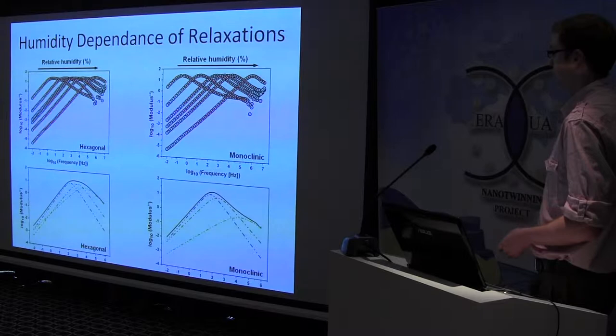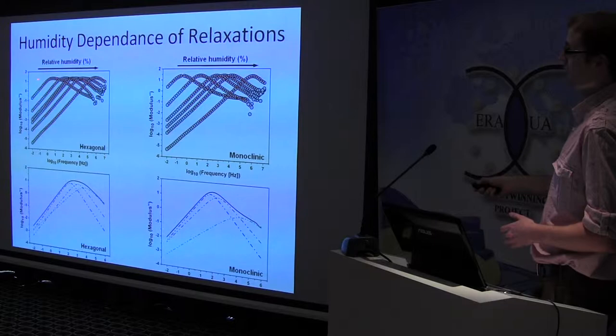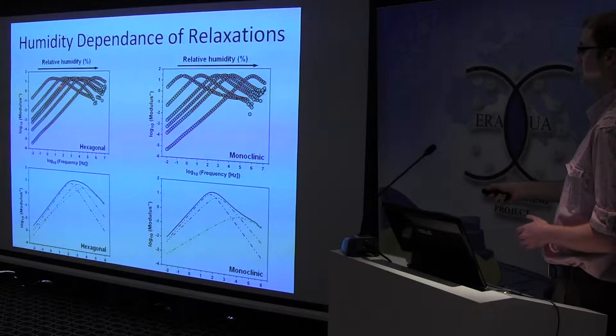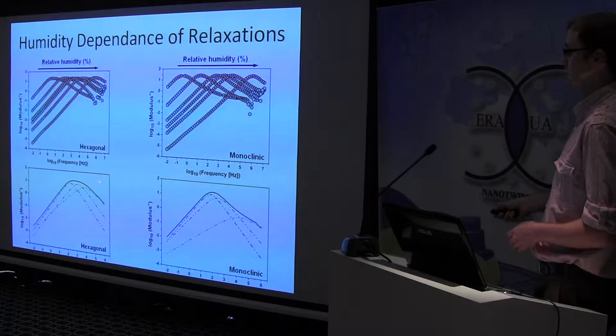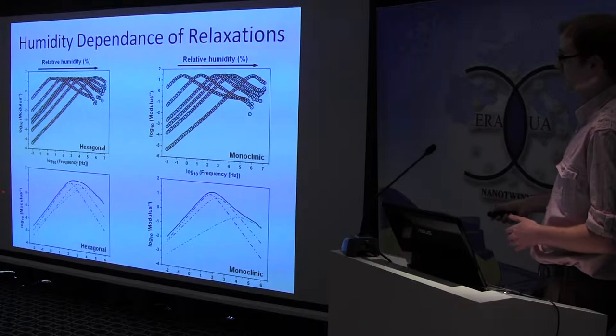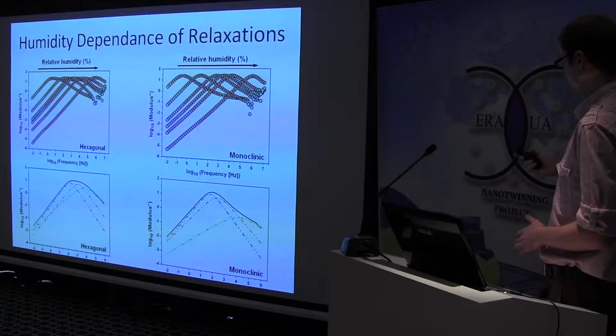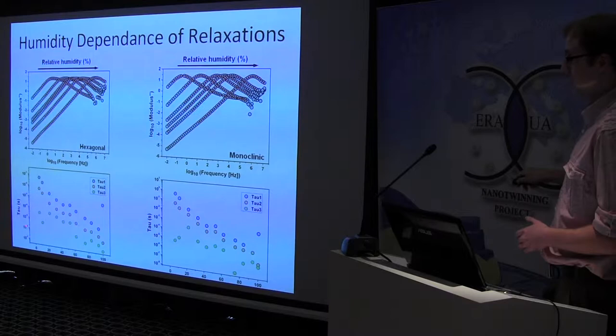Here you can see the humidity dependence of the dielectric response in modulus representation. Here is the sample at 6% of relative humidity and this is the sample with 100% of relative humidity. You can see that there is a shift to higher frequencies with increasing relative humidity. Here you can see a single modulus which consists of three different relaxations with three different characteristic relaxation times. And these relaxation times were also plotted as a function of relative humidity. And you can see that the relaxation times of the processes decreasing with relative humidity.